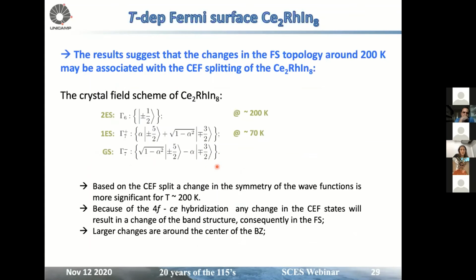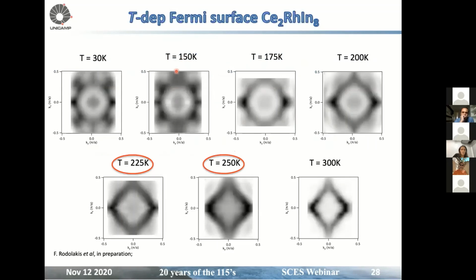And those results suggest that changes in the Fermi surface topology are associated with the fact that we are changing from gamma 7 states to a gamma 6 one. So the big change in the crystal field here is the big change we could see on the Fermi surface topology. So just pointing out that we don't see change at all from basically 150K to low temperature.